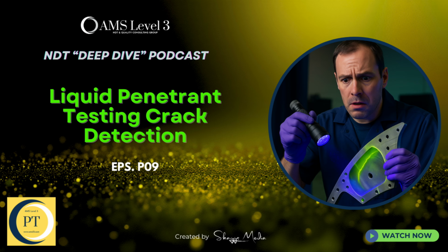Makes sense. Now, we've already established the big limitation: liquid penetrant testing only finds flaws that are open to the surface. Are there other limitations maybe related to the shape or geometry of the flaw? Yes, there are. Remember how capillary action works best in tight, narrow spaces? Right. Well, if you have a discontinuity that's very wide but also very shallow, where the width is much greater than the depth, that might get missed. Why is that? Because that wide, shallow opening doesn't create a very strong capillary pull, and it doesn't hold much penetrant. What little penetrant does get in might evaporate too quickly, or it might get washed away too easily during the removal step. There's not enough reservoir to create a strong bleed out. Okay, so wide and shallow can be problematic.